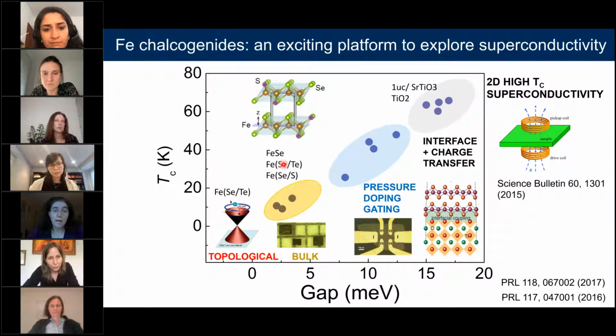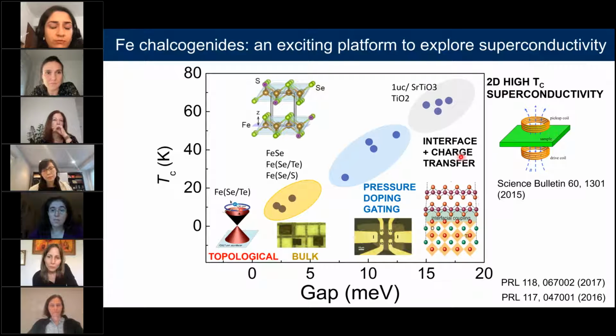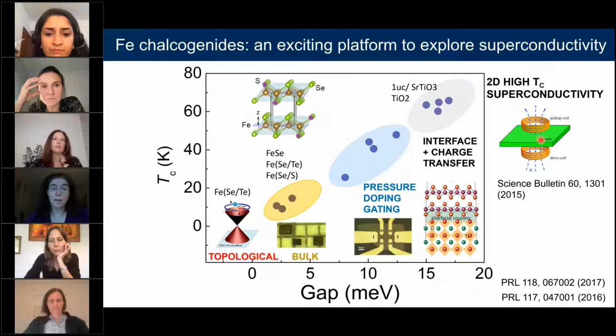And these iron chalcogenides are a new exciting platform to explore superconductivity, because not only can we explore them in bulk single crystals, but they also now have a huge ability to be tunable. We know that in a monolayer on strontium titanate, the superconductivity of iron selenium becomes extremely large, close to 100 Kelvin. Some of the reports are around 75 Kelvin. So this extremely high two-dimensional superconductivity is very exciting, with potential applications.